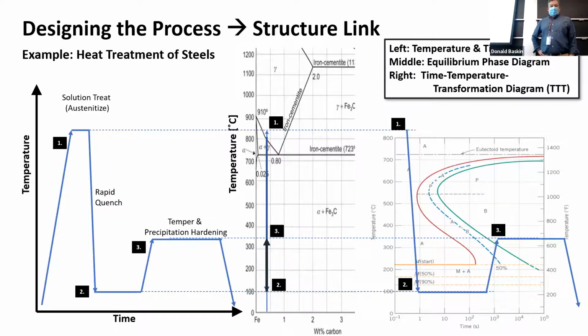Steel. We just talked about steel. Take a piece of steel that might be fresh from the mill or something, and you heat it up to 870 degrees, and it turns to austenite. You quench it down to room temperature or somewhere about there, and most of it will transform to martensite. Some of it will stay austenite, which actually can be useful in some cases. But you transform it to martensite, and the martensite is much stronger.